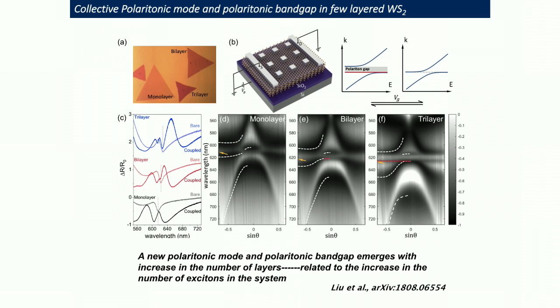But when we go to the trilayer case, something very interesting happens, and that is, there is this flat line, this dark mode that you see. This is a function of angles, which basically means in-plane momentum of the excitation. So this mode that occurs in the system, which does not exist clearly in the monolayer, starts to emerge in the bilayer, but is very strong in this trilayer, is flat and dispersionless. It does not disperse as a function of in-plane momentum of the system. Then there is this bright region that you can see, this flat bright region.